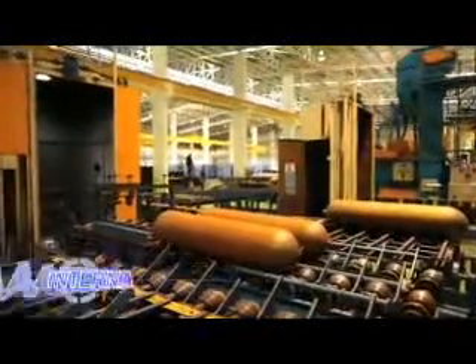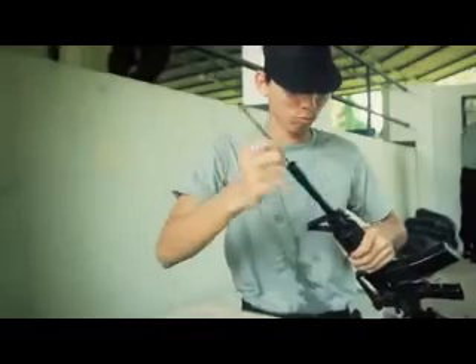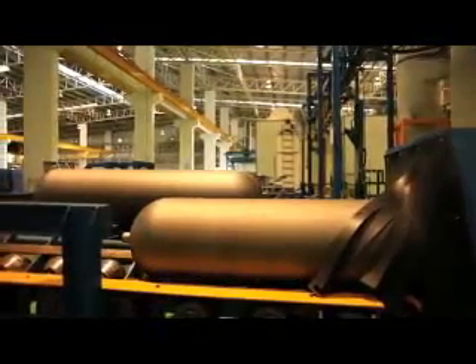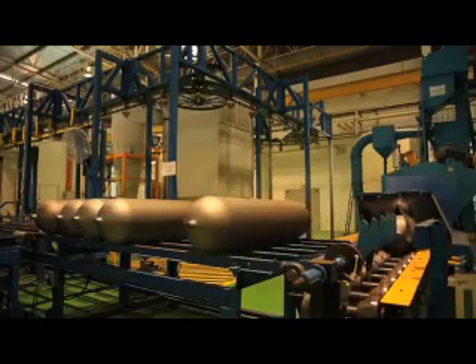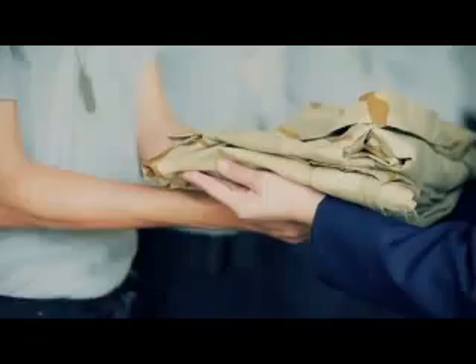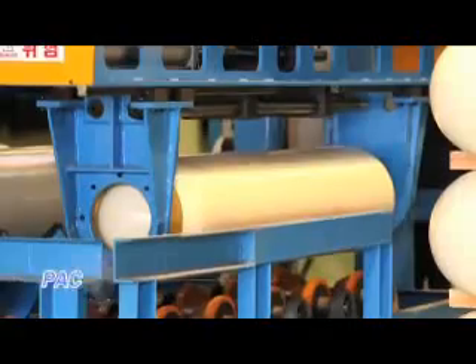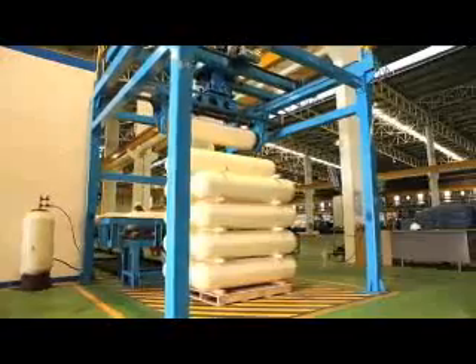Internal shot blast: internal shot blast is processed for cleaning scale and rust inside the cylinder. External shot blast 2: second external shot blast to improve the surface and final cleaning before painting. Painting: powder coating painting, oven booth temperature 180 to 200 degrees Celsius. And lastly, packing: to pack and organize the product orderly.